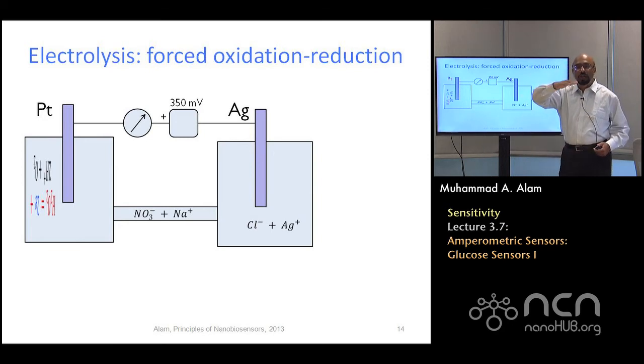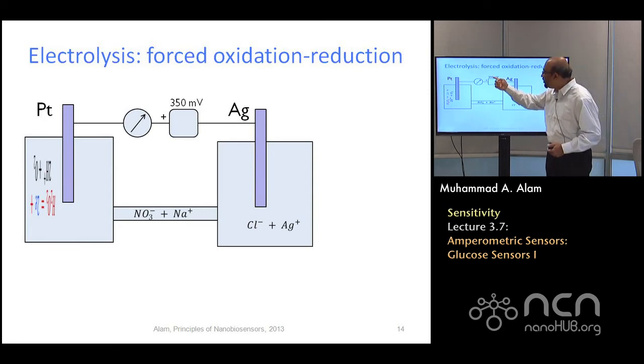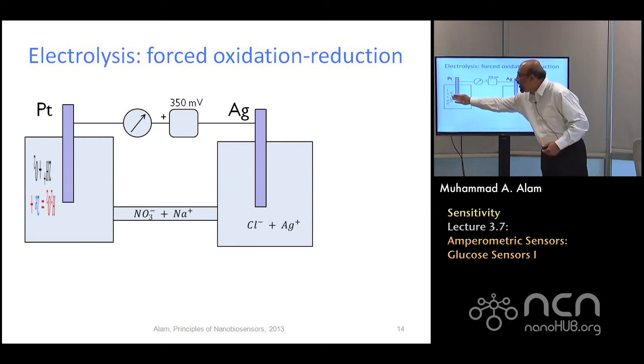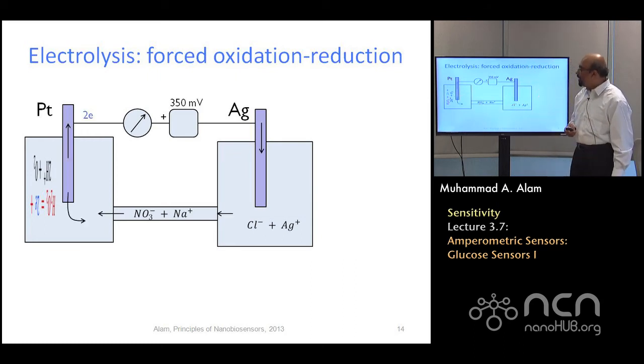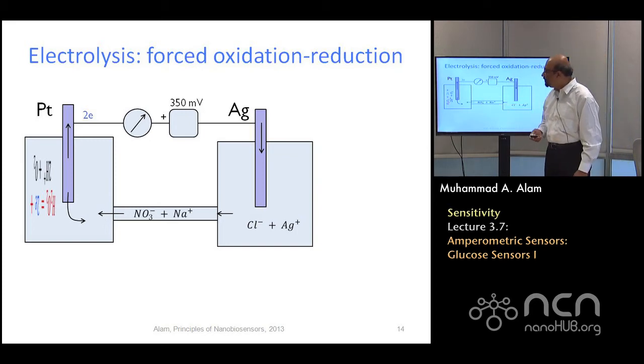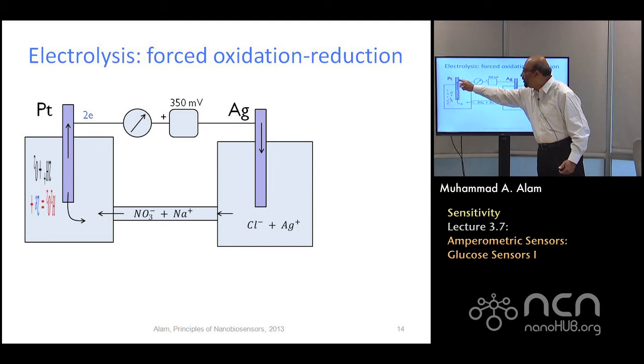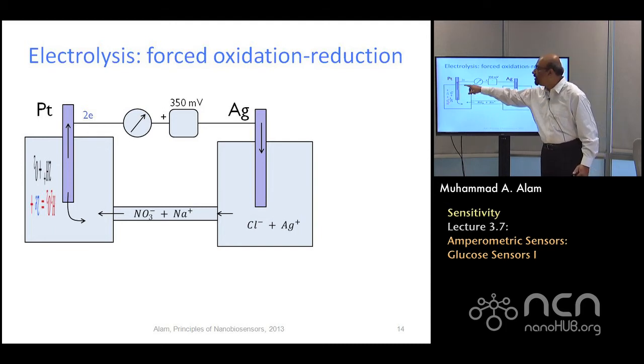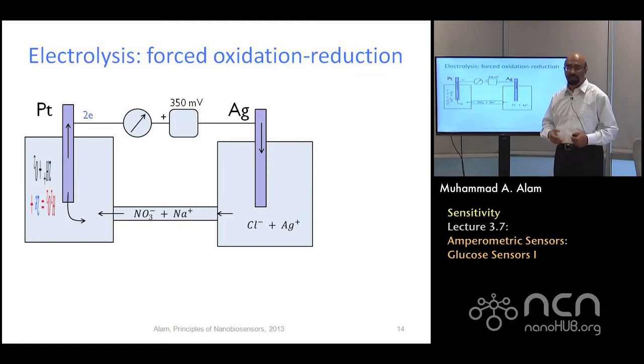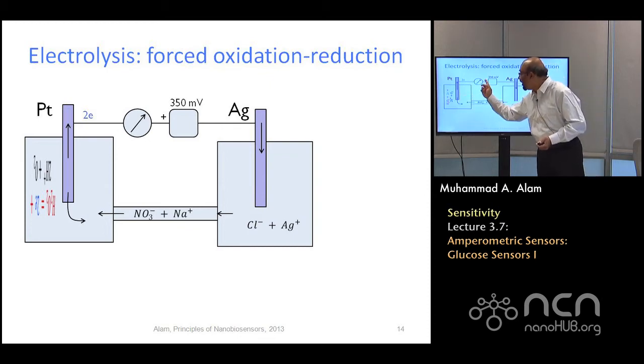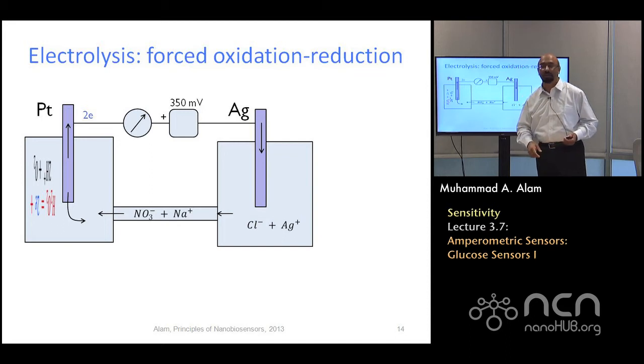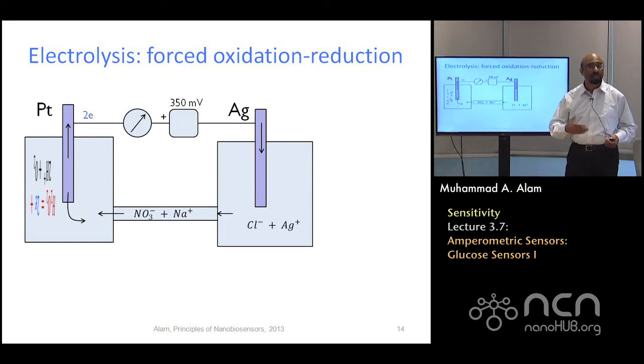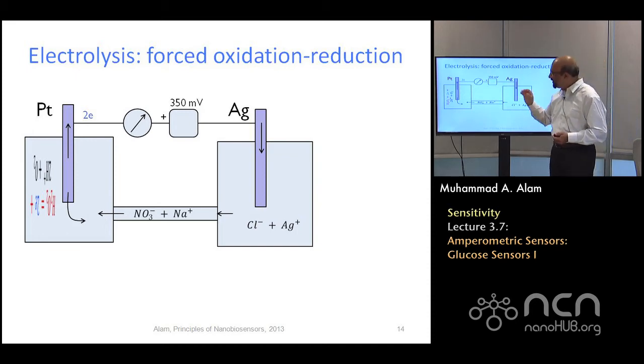Hydrogen peroxide will have lower oxidation potential, and so as soon as you apply 350 millivolts, this reaction will begin. The proton will come this way, and the electron will go, and this process will continue. Although it's not a spontaneous process, with this applied voltage it becomes much easier for this reaction to proceed. And so this current becomes directly proportional to the hydrogen peroxide concentration, which is also directly proportional to the glucose concentration. So this is how the sensor would work.